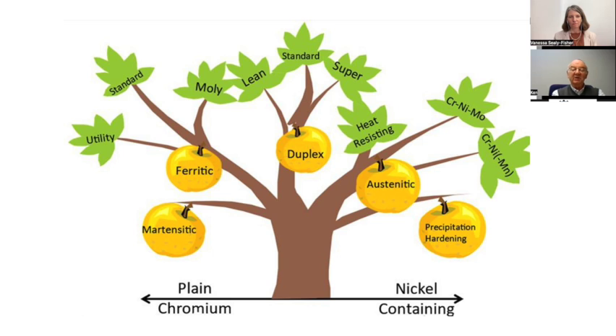The standard duplex, on the other hand, is a grade that we know with the general terminology of 2205. It's referred to as standard duplex stainless steel. So nominally it's 22 chrome, 5 nickel. There's some molybdenum and nitrogen added as well. So again, that molybdenum and nitrogen and chromium present will give you your pitting and crevice corrosion resistance. And again, its corrosion resistance will come about from the alloying elements that are there.